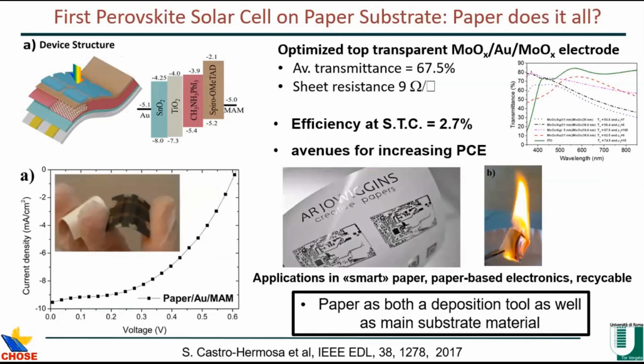This is my last slide. We showed the first perovskite solar cell on paper. And here the trick was using some transport layers which were compatible with paper substrates, and a top electrode which was transparent, made with molybdenum oxide, very thin gold and molybdenum oxide. The initial efficiency was 2.7%, but paper is recyclable, low cost, and in a way skin biocompatible. So we could think of using paper not only as an applicator, but as a substrate material.